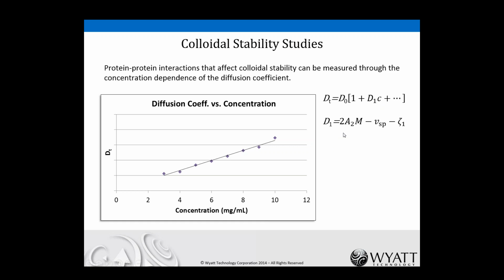The nice thing about D1 versus measuring A2 is that it can be measured in micro-well plates very rapidly and very efficiently. Here's a relationship between D1 and A2 and the different nomenclatures. So you might see k sub D in the literature. I prefer to use D1 just so we don't confuse it with some other parameters that look the same. And if D1 is positive, generally it's repulsive behavior. If it's negative, it's generally attractive behavior.